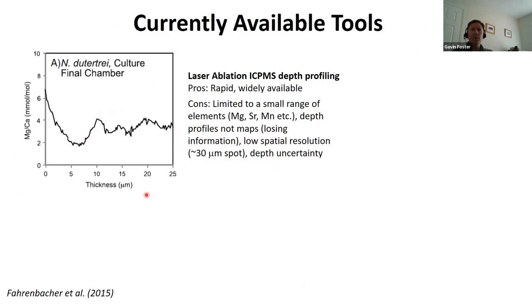We use laser ablation ICP-MS to do depth profiling, which is one way in which we can look at individual shells. In this case, you ablate from the outside in using a sector field or a quadrupole ICP-MS. You're limited to a small range of elements, because you don't want too big a mass range, as you end up with the problem of transient signals. Also, turning time into depth is not necessarily straightforward. You're also losing information because you're just doing a profile, and you tend to use a large spot, 30 microns or so, to get sufficient precision, so you lose a lot of spatial information. You do get some idea that there's zoning within the shell, but it tends to be a bit smeared out.